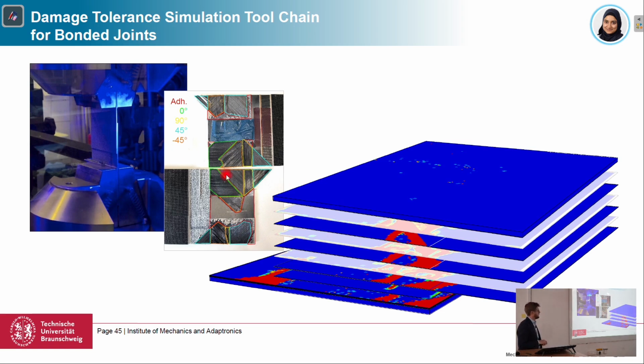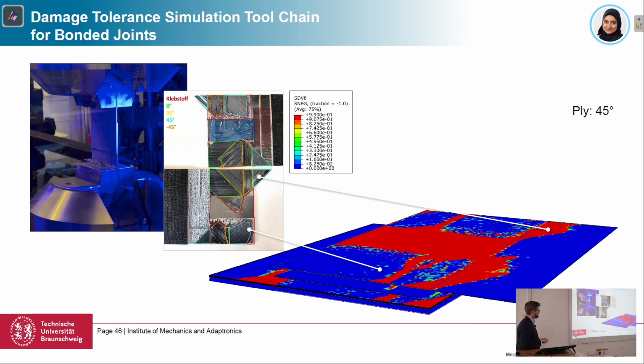And this test was also simulated with our simulation tool chain and the residual strength simulation. And it not only predicted the strength and stiffness of the specimen quite well, but also the damage pattern. For example, here is a 45 degree ply where we see this damage inclined by 45 degree, and this corresponds well to these areas which are also 45 degree plies. So we could also predict the damage pattern after the test.